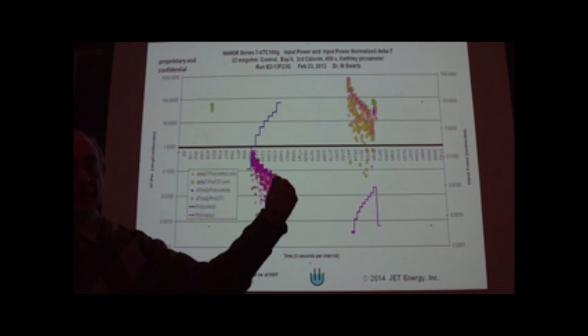Those kilograms, are they the NANOR kilograms or the active PD? No, this is calculated. There are no kilograms. We have milligrams. We have 30. I think the biggest NANOR we're running right now is about 150 to 200 milligrams. But you have zirconium oxide as well as the nickel. So how much? On the basis of the whole mass, that's the 19 kilowatts per kilogram. On the basis of the palladium alone, that's where we get around 68 kilowatts per kilogram. It goes from 19,000 to 68,000. That's whether you have the whole mass or just the palladium.